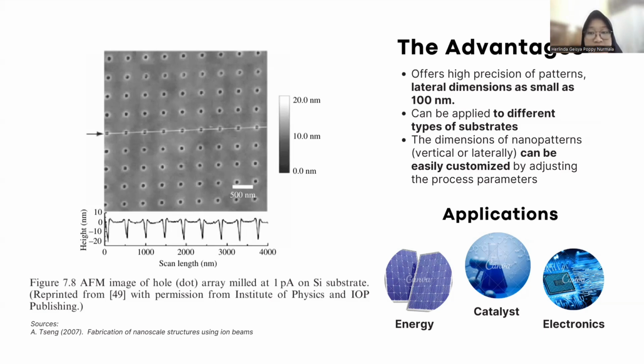We can also see that the smallest features in the image are around 100 nanometers compared to the spacing between the nanopatterns, which is consistent with the nanoscale precision achievable by using ion beam techniques. The graphic below shows the variation of the height profile, indicating the height can be precisely controlled due to the several factors explained before.